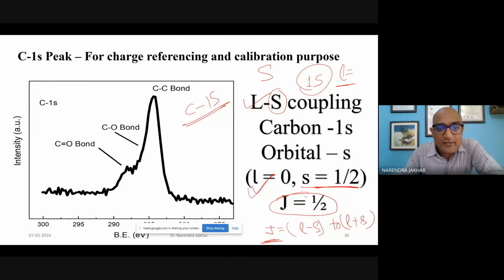And here you can see that this 1s peak of the carbon shows some asymmetric nature, and this asymmetry reflects that there are different chemical environments in this carbon. The first, on the lower binding energy side, is the C-C bond. The second hump is there; you can fit a particular peak there, and this is responsible for the C single bond O. A separate peak you can fit here, and a peak here.